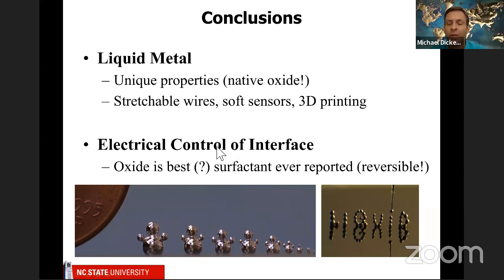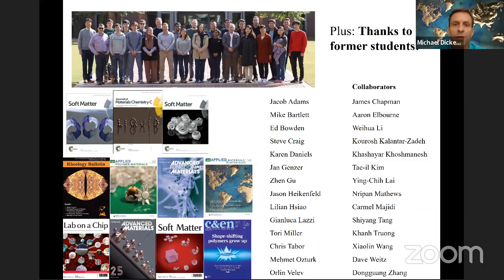temperature. And then the last part of the talk was to show you that we can change the surface tension from the largest tension possible as a liquid to basically zero using 1 volt. And so I think that this suggests that the oxide is, quote unquote, the best surfactant ever reported, and it's reversible. This work was done with amazing students here at NC State.